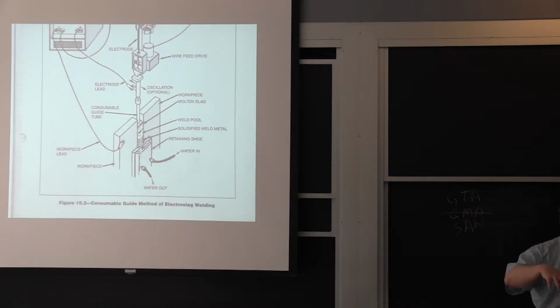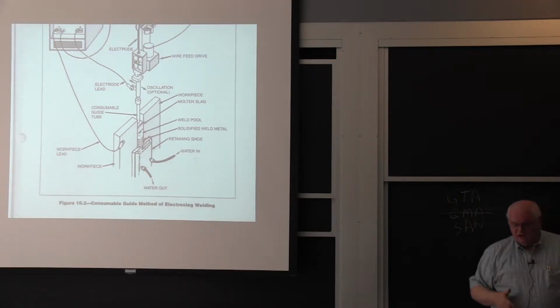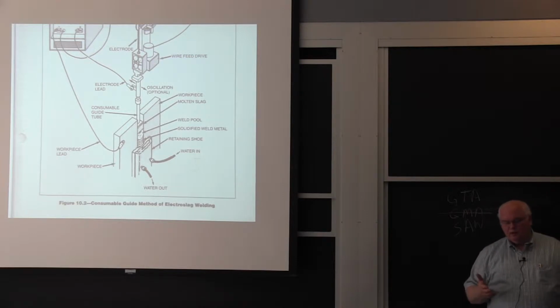Maybe 8 welds. But they have a whole facility down at Quonset Point to get that extreme circularity you need for a good pressure hull. In steel, they have an indoor building that costs $200 million down at Quonset Point so they can weld these things. And so they weren't using Electro Slag, they were using Gas Metal Arc on the steel, but you could do that with Electro Slag.